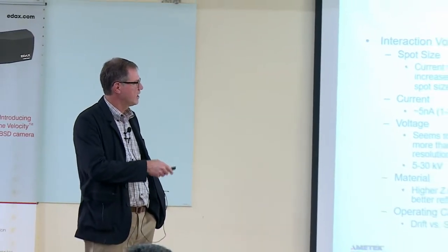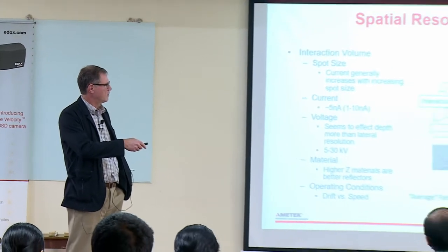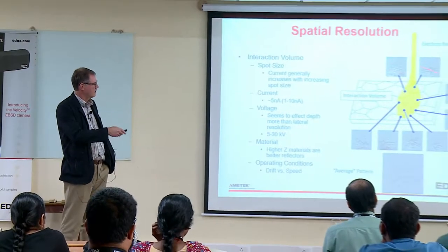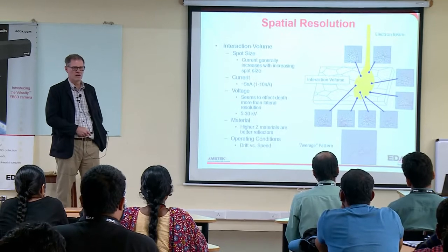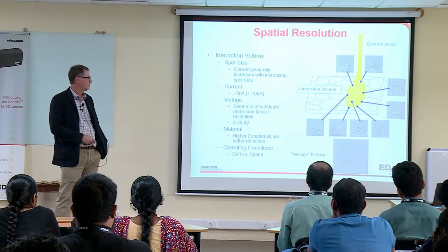So one of the things is spatial resolution, and we need to talk about this. The electron beam comes in, and if our material has a lot of grains, or fine grains, then our interaction volume may contain several grains. Each one of those would give a nice pattern by itself, but if our interaction volume contains all of it, then it's essentially the average of all these, and we get a poor pattern, basically an average pattern that makes it very difficult to index.